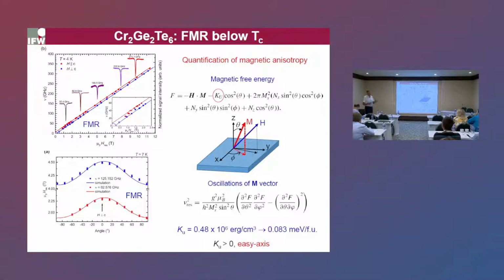In electron spin resonance, one measures the response of the individual precessing spins. They could be coupled by exchange interaction, but nevertheless, there is a response of the individual spins. In ferromagnetic resonance, this is a response of the total magnetization of the sample. So the magnetization precesses around the applied magnetic field, and one can drive these oscillations by applying microwave radiation of an appropriate frequency. And we could model the development of these ferromagnetic resonance modes by calculating the oscillations of this magnetization vector, which are given by the angular derivatives of the free energy.